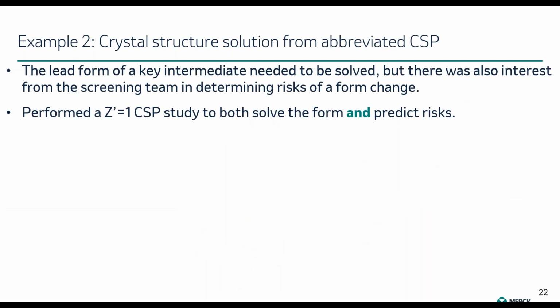A second example is where we did a crystal structure solution, not from a targeted, but for an abbreviated CSP. So in this case, the lead form of one of our key intermediates needed to be solved, but we also had interest in determining the risk of a late form change. So we wanted not just to solve this crystal structure, but we wanted to place it on a crystal energy landscape to see whether there was any threat, any more stable threat.